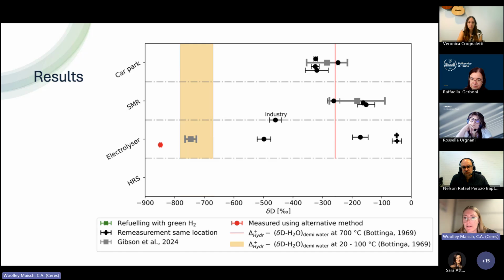We thought everything else is agreeing with the literature, the electrolyzer should too. And then we have some points here somewhere in the middle. I should also point out that this data point here is from a commercial electrolyzer, so they are operating 24 hours a day, 5 days a week. And this one here is a lab one. So this begs the question, can we really distinguish between blue and green hydrogen with delta D, because this point here falls exactly into the range that the SMR should be falling into.